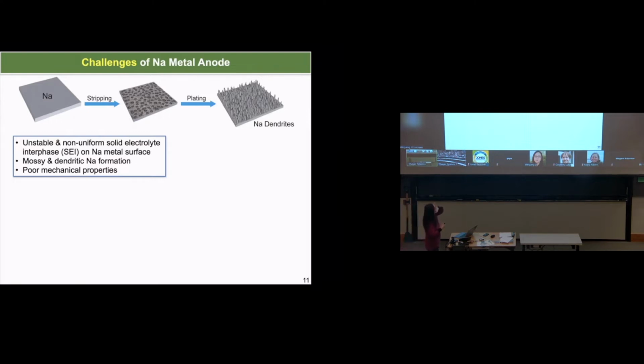Sorry, I forgot to mention why dendrite is dangerous. Dendrite is generally a mossy or sharp dendritic structure, so it can actually penetrate the separator, and once these dendrites contact your cathode material, you are going to get a short circuit of the battery system, and then it can cause a fire. Okay, you have heard a lot about battery fires in the news. It's mainly also due to lithium dendrites. Lithium actually has a similar issue. The lithium dendrite can also form in the lithium battery system, which causes a fire.